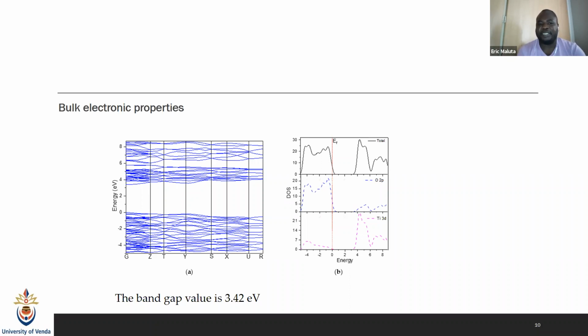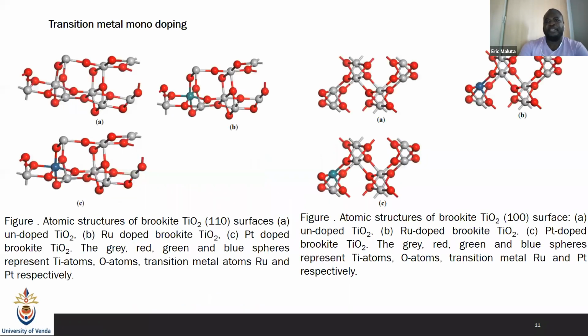And for the bulk property here, our band gap, as I said, is very high. For the calculated one, the band gap value is about 3.42, which, when we look at the absorption of the TiO2 Brookite, means it's absorbing in the ultraviolet, which for solar cell application is not needed. We need it to absorb from the visible light to the near infrared. And then the DOS just shows us the contribution of the oxygen atom and the titanium atom before introducing other materials in the system.